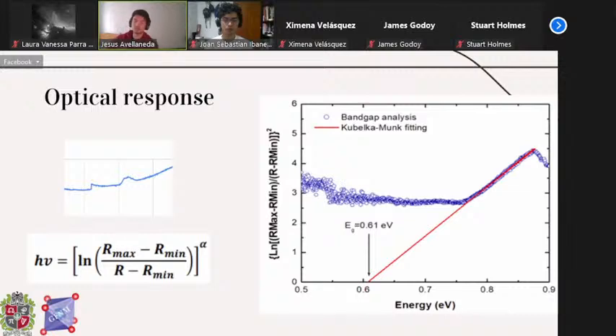Basically, when the incident energy is within a certain threshold, this energy causes a vibration in the bonds of the material. These peaks are static, so they can be seen in both graphs obtained. They didn't change position between absorbance and reflectance curves. So that was a curious thing to analyze. With the data from Rietveld and VESTA, we obtained the bond distances within the material. As an analogy, let's think of the bonds as if they were strings. So the higher the vibration energy, or the energy that reaches the said bond, the shorter the bond, and vice versa. But that was a plus analysis for the important analysis of this part.